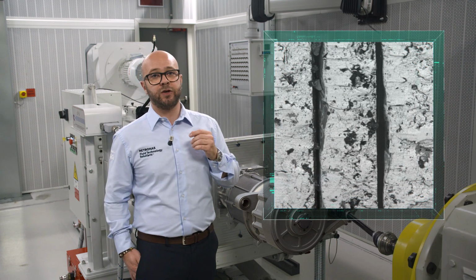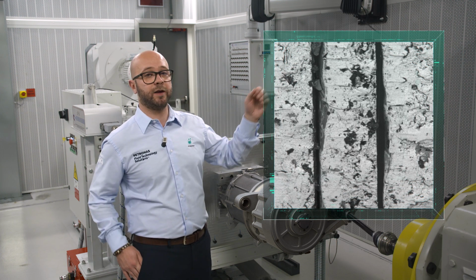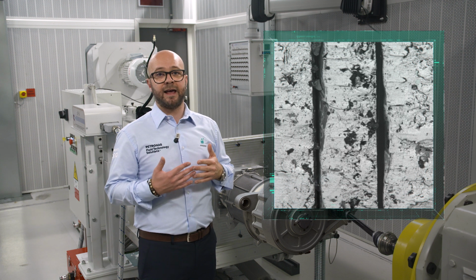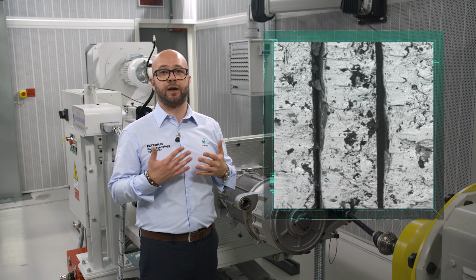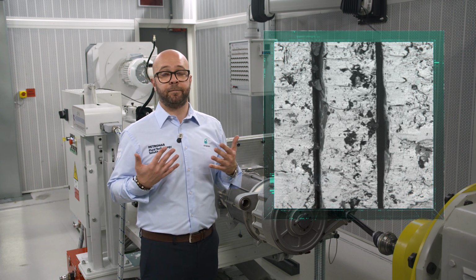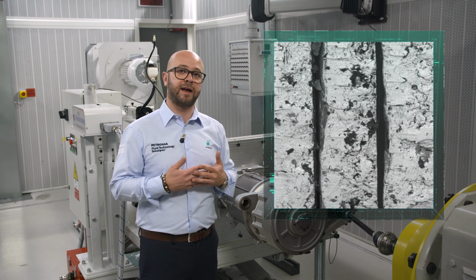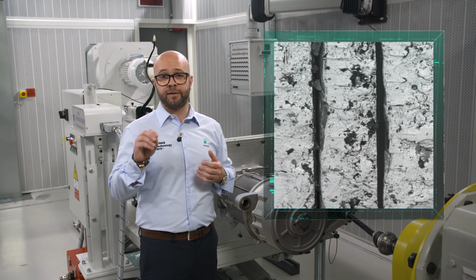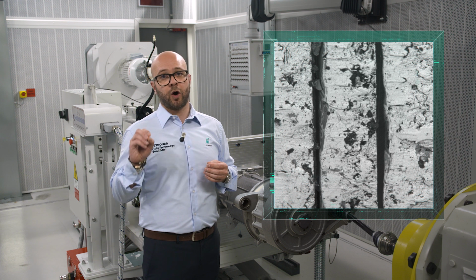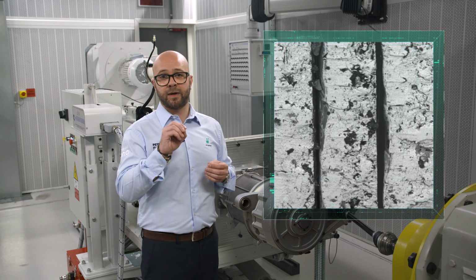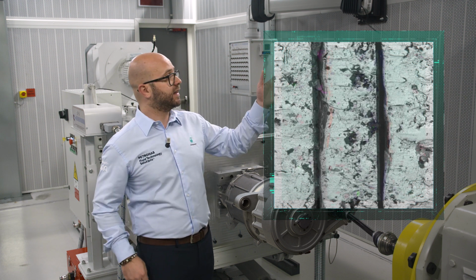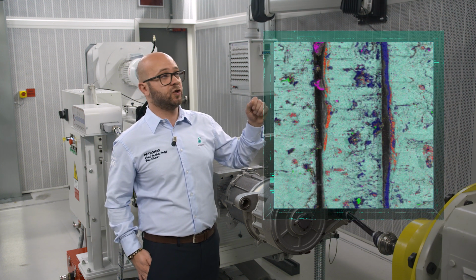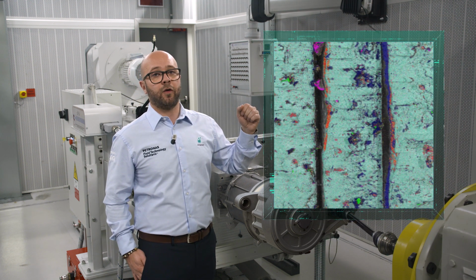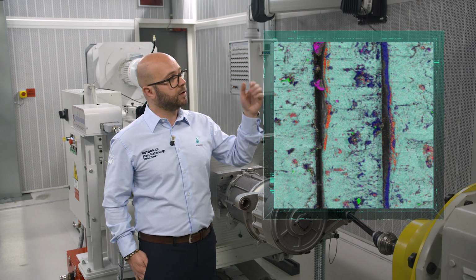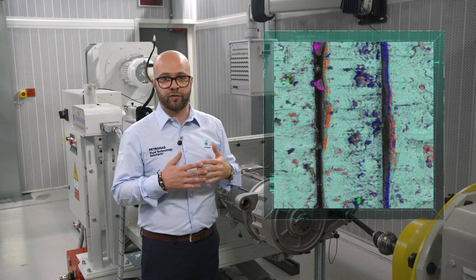More interesting is when we move to microscopic dimensions and we have the SEM image. The SEM image of the part exposed to the liquid is very bright and suggests that the surface is still mainly constituted by iron, and we only find some residual oil in some small regions. We can see from the EDX image that in fact the color of iron is present widely on the surface.